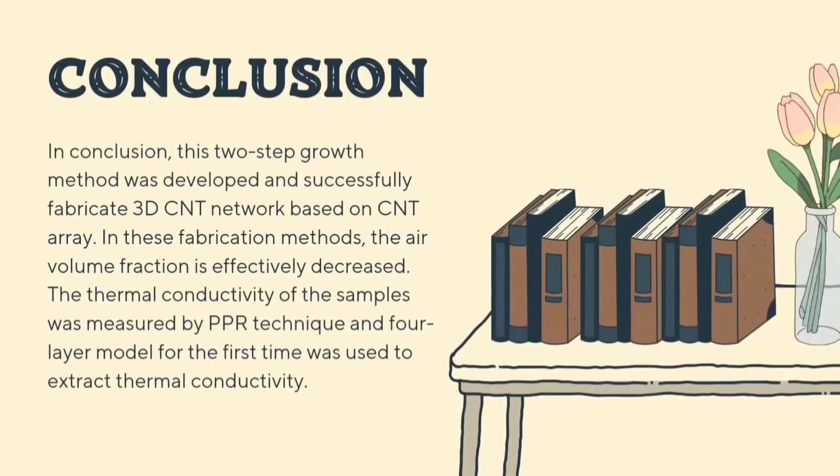In conclusion, this two-step growth method was developed and successfully fabricated a 3D CNT network based on the CNT array. In this fabrication method, the air volume fraction is effectively decreased. The thermal conductivity of the samples was measured by the PPR technique, and a 4-layer model was used for the first time to extract thermal conductivity. The samples were covered by a C layer, and the layer adhered very well to the CNTs by strong covalent bonds with low thermal contact resistance.